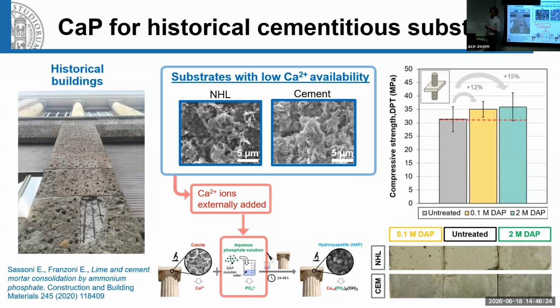In general, the idea is that also in the case of cement or natural hydraulic lime, we have a substrate containing some calcium-based minerals. There's calcium carbonate. In this case, as you know, we have CSH, calcium silicate hydrate, a mineral that is less soluble than calcium carbonate, so it can provide less calcium. But to solve the issue, it's possible to add calcium ions directly into the DAP solution, okay? So it's possible to favor the formation of calcium phosphates.